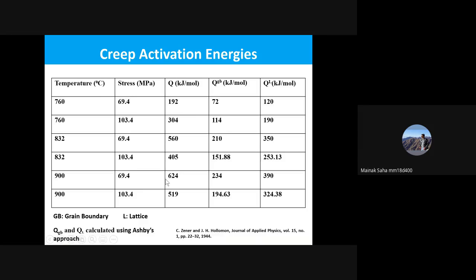So what interesting observation can we see? This has been calculated from the total Q. The QGB and QL have been calculated using Ashby's approach, and a very good formula for calculating such components of Q can be easily found in this particular work. The paper is from very long back, but it definitely provides a lot of inputs about calculating the value of creep activation energy. So from this, the interesting observation that we can get is as follows.